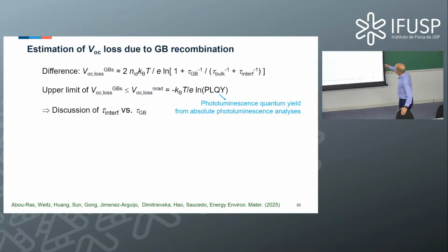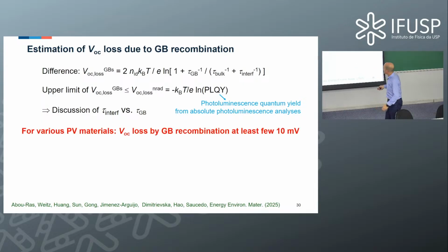And actually, if you put this in this equation here, you can calculate the total loss of non-radiative recombination of an open circuit voltage, right? And that's the upper limit, basically, of the open circuit voltage loss of what you have at grain boundaries. And this actually gives you means to discuss the impact of the grain boundaries or the grain boundary lifetime, yes, with respect to bulk lifetime and the interface lifetime, right? That means basically it gives you a range of these lifetimes, and you can actually discuss that or find that the VOC loss by recombination at grain boundaries is at least a few tens of millivolts, even for the best solar cells. Yes, but of course always reaches a certain maximum that depends on the photoluminescence quantum yield of the material.